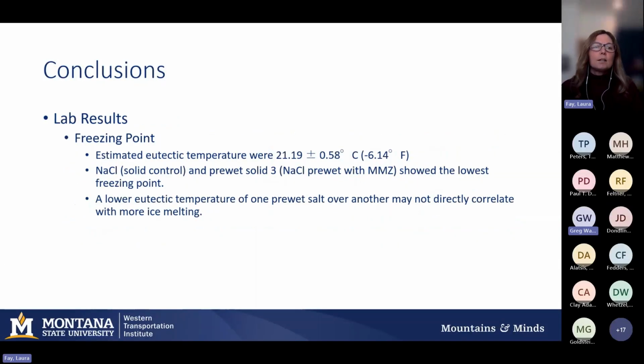So from the lab testing, what we can say about the freezing point results or the estimated eutectic temperature is that because they were all basically salt-based products, sodium chloride-based, they had very similar eutectic temperatures. So around -6. And that from this test, rock salt and pre-wet salt with Magic-0 showed the lowest freezing point. But again, when you look at the error or the standard deviation here, it was very minor. These were all within a degree or two of each other in terms of eutectic temperature.